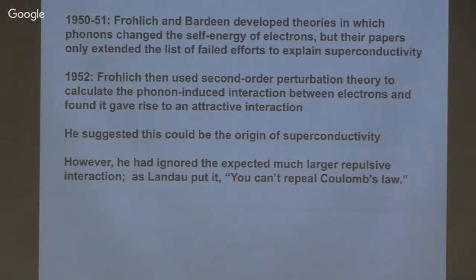Well, the first pass was made independently by Herbert Frohlich and John Bardeen, whose passion was to understand superconductivity. And they failed. They thought it was the self-energy. The electron moves along, emits a virtual phonon, reabsorbs it, that changes its mass, and they tried to argue, well, this is what gives us superconductivity. Doesn't work. Frohlich then said, well, maybe if you go to second-order perturbation theory, you can calculate the phonon-induced interaction. An electron emits a virtual phonon, a second electron receives it, so you can think of it as a polarization effect. This gives rise to an attractive frequency-dependent interaction.